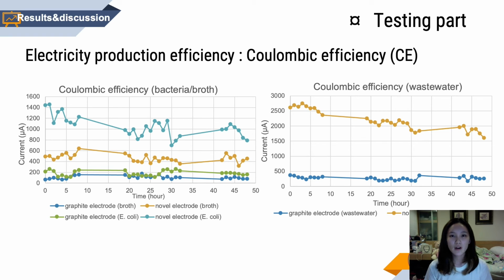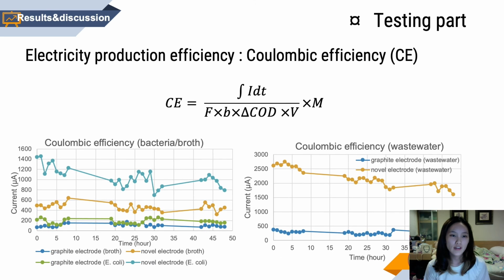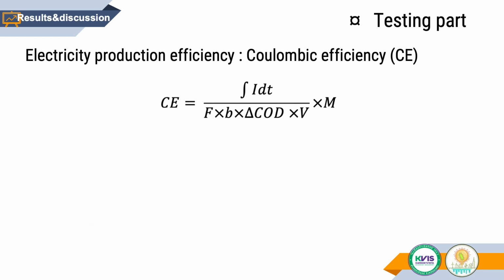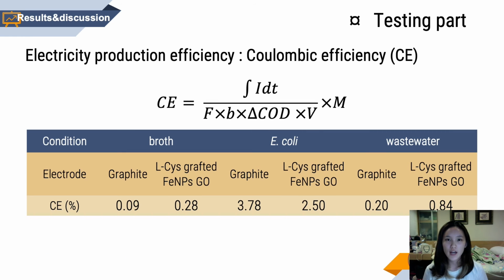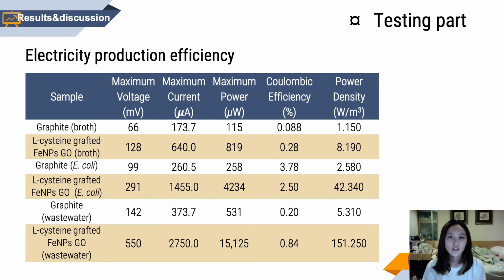For the electricity part, we measured the current produced from the actual MFC using our novel electrode compared to the normal graphite electrode for 48 hours in three conditions, which are broth, E. coli, and wastewater. Here is how we calculate the Coulombic efficiency, which is the efficiency of producing current per one unit of wastewater treatment. In wastewater, you can see that our novel electrode has a Coulombic efficiency of 0.84, which is 4 times compared to the graphite electrode. Here is the overall result of what we measured for 48 hours.